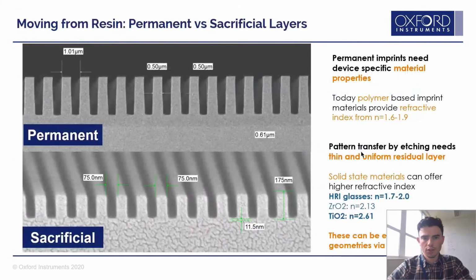It's not just the geometry we need to consider though, it's the material itself. So currently we use polymer-based resins. We can make a stamp via lithography and etching and stamp a grating shape into this resin, and that gives us our waveguide. This is a permanent resin layer. The resin is placed, stamped, and becomes our product. But they only have refractive indices from 1.6 to 1.9.